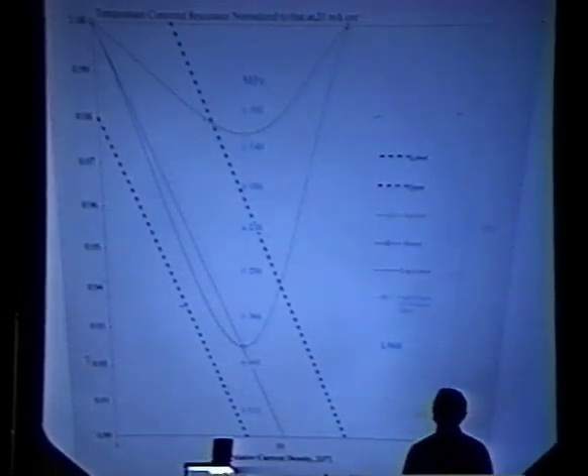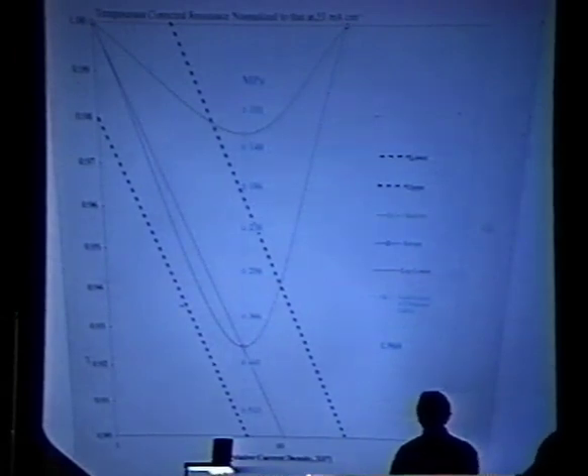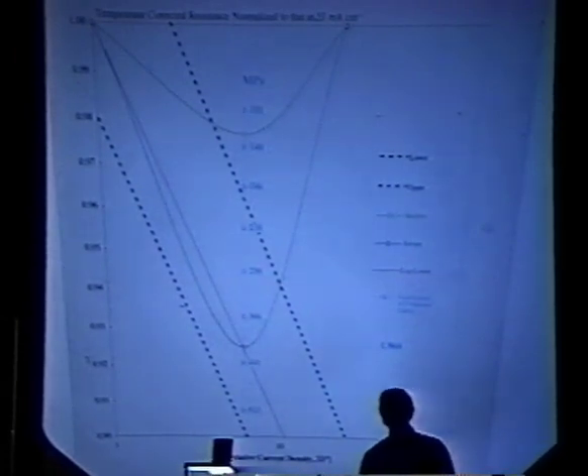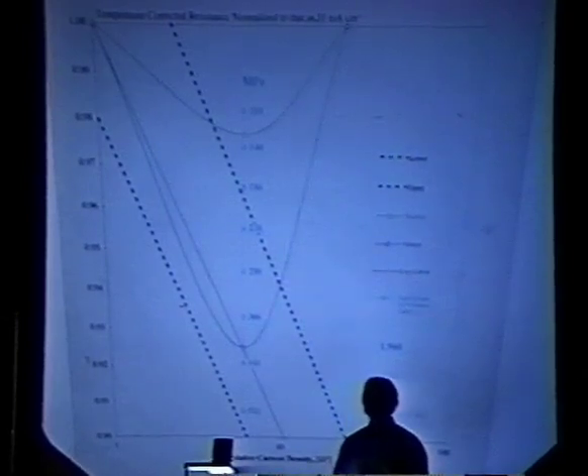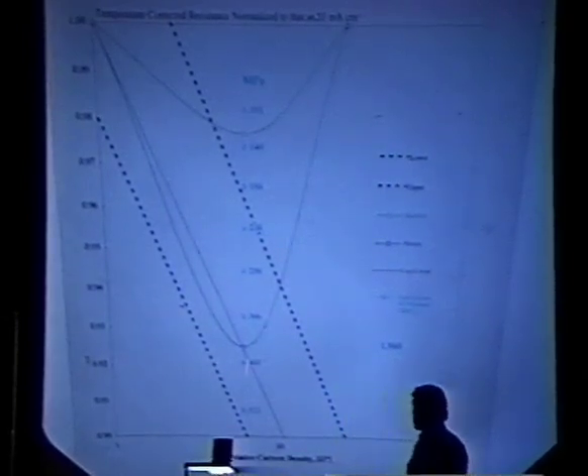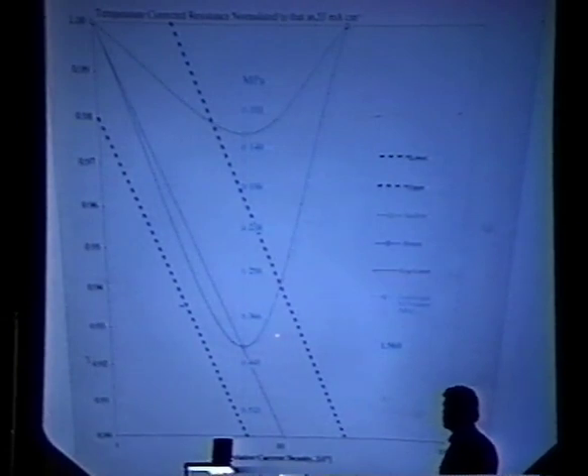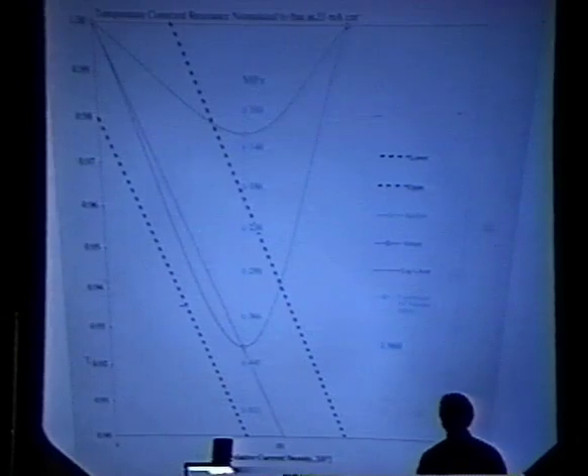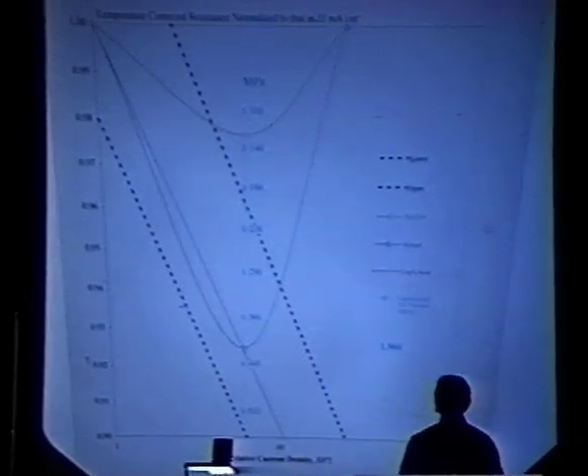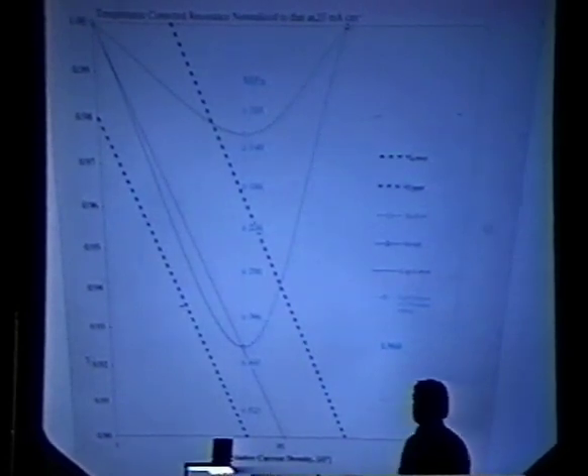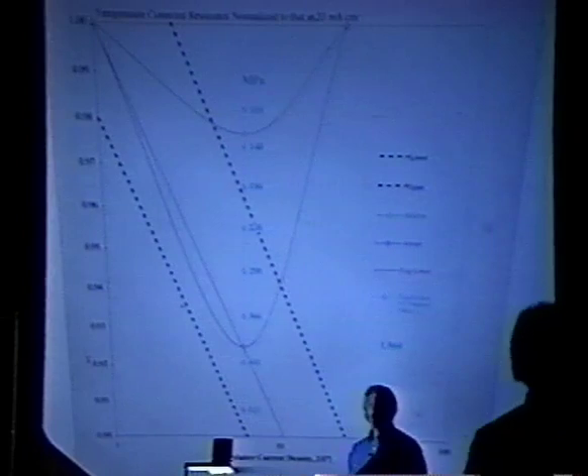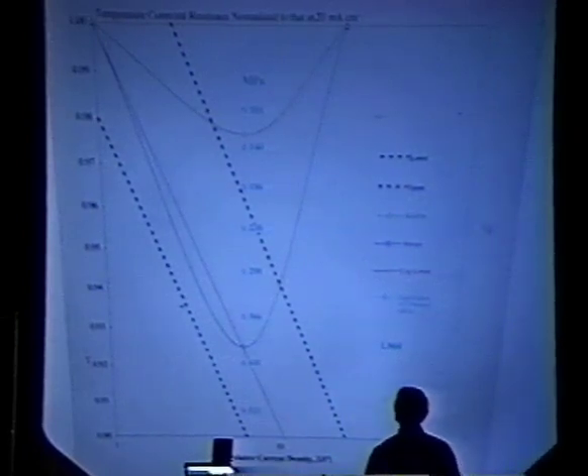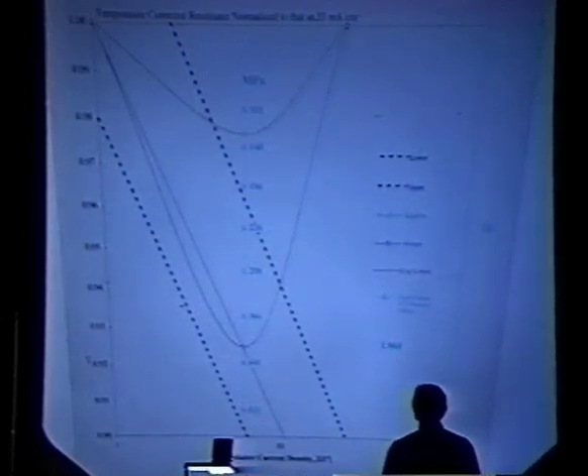I submit that the failure is mechanical. There are voids inside the palladium, which when loaded to these pressures, simply yield, and this is a number close to the yield strength of palladium. We don't actually know what the yield strength of PdD 0.9 is. This is a number not unreasonable for the yield strength of palladium. So I'm submitting that the mode B behavior fails mechanically.